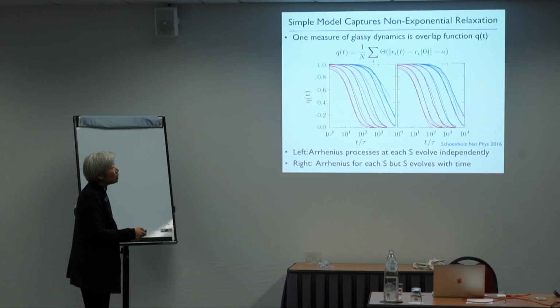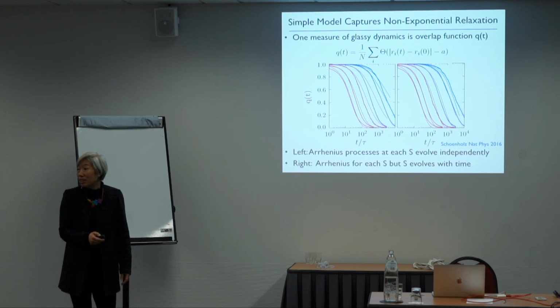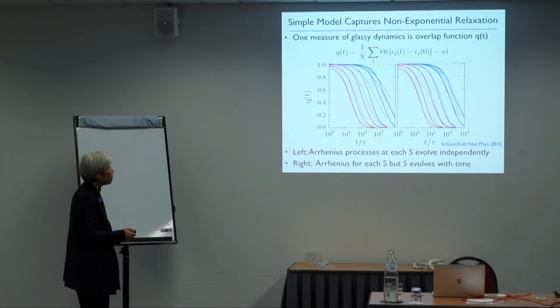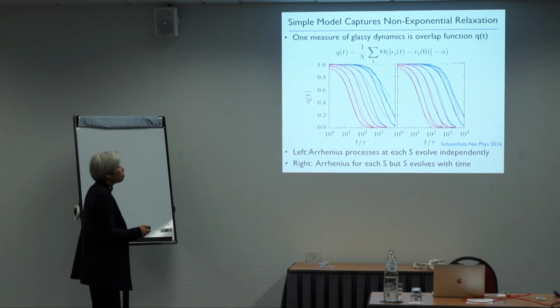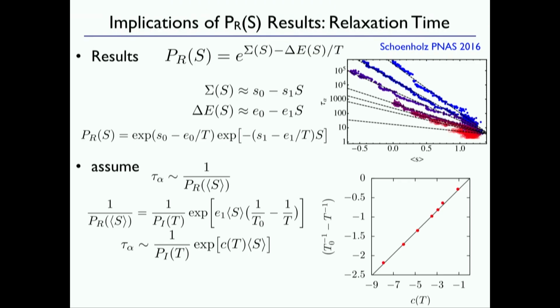So it's a diffusive process, and we just put that in. So it's a very simple theory. Again, we're not tracking each particle. We're just saying, I'm just going to assume that it makes a random walk, and put that in, and that does extremely well. Not only does it capture the time scale very well, but even quantitatively it works very well to describe that. So we can get the non-exponential relaxation.